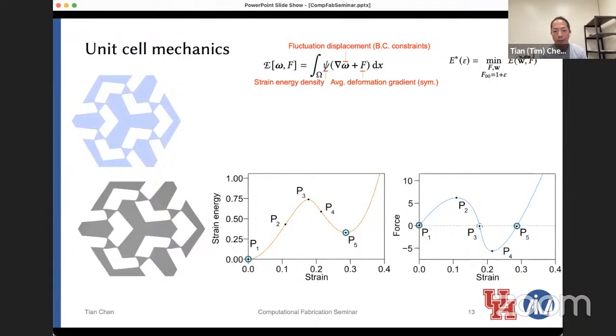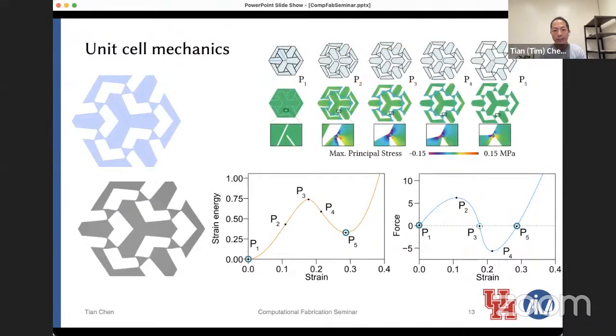Knowing the mechanics of the unit cell, we have different criteria that we can use to pick our most ideal unit cell for the purpose. First, we can see that the strain of the hinges plays a significant role in determining the stiffness of the structure. The first choice we have is the difference in energy between the unstable equilibrium, some sort of intermediate state, and the second state, which is the deployed state.